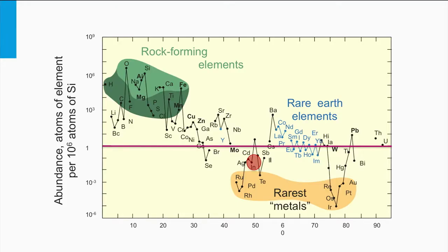Here we see an illustration that shows the abundance of the various elements in the Earth's crust. The red line is an indication for the critical abundance of a source material to be used for a large-scale production. As you can see, indium is not a very abundant element as it lies below the red line. Therefore, indium might be the limiting step to upscale the CIGS PV technology to future terawatt scales. In addition, the current display industry depends on indium as well, as ITO is integrated in many display screens.